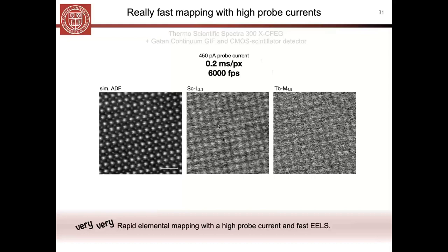You might say that while these maps look a bit noisy, the atoms aren't quite as clear as they were on the previous maps. While that's true, again, what we want to do is go beyond just identifying atomic positions. We are really interested in starting to extract very detailed information from these sites. If you want to get a really clear picture of what's going on, you can do some unit cell averaging. Here I've unit cell averaged across this field of view, and you can see that the atomic structure pops out very, very clearly. And what's exciting is that because the frame time for this map was so fast, the deformation across this single scan is actually very, very small.